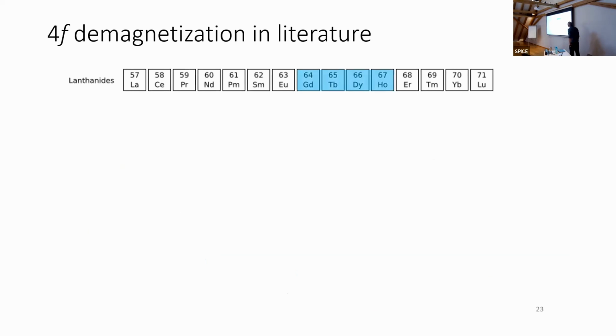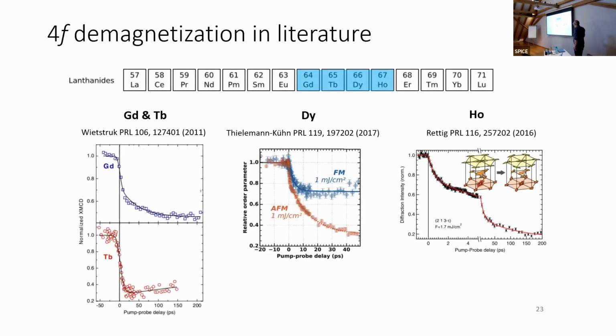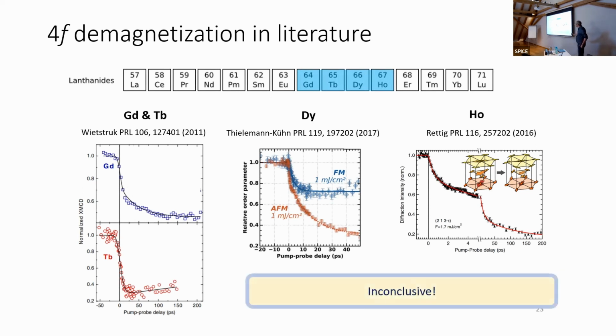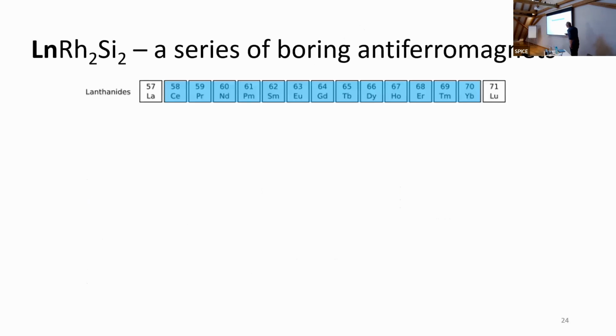If we look at literature and try to find a reasonable comparison between dynamics of 4f systems, we can find these examples. These are pretty much the only examples, except for lots of optical work on gadolinium. Unfortunately, this is very inconclusive because the conditions of these experiments are extremely different. This is a single crystal. This is a thin film, but it's very thick compared to these, which are very thin and comparable to each other. So unfortunately, we can't really easily do that.